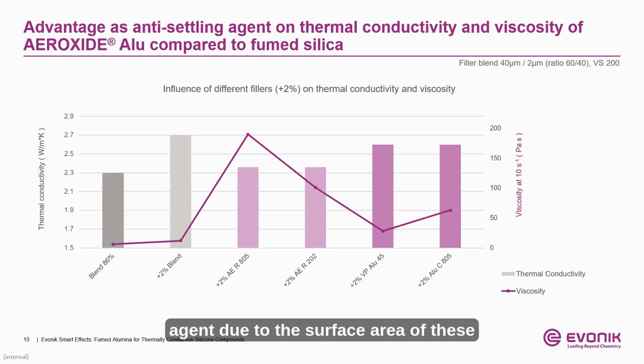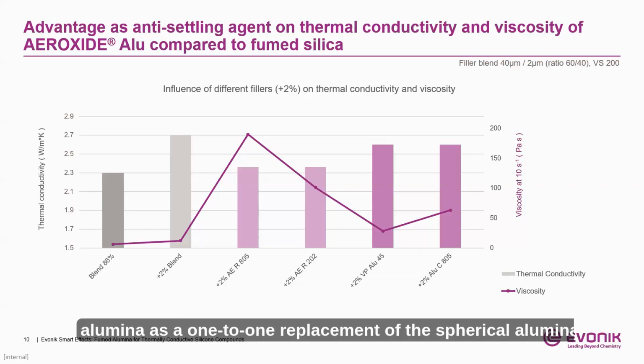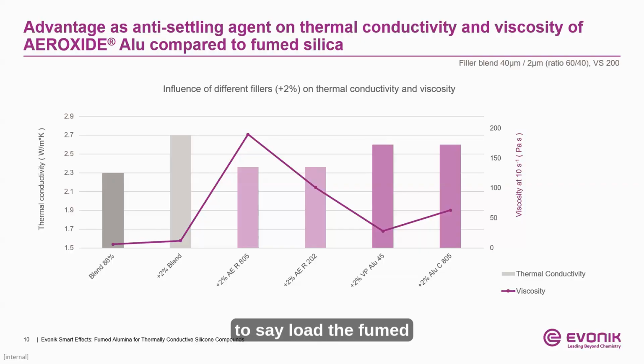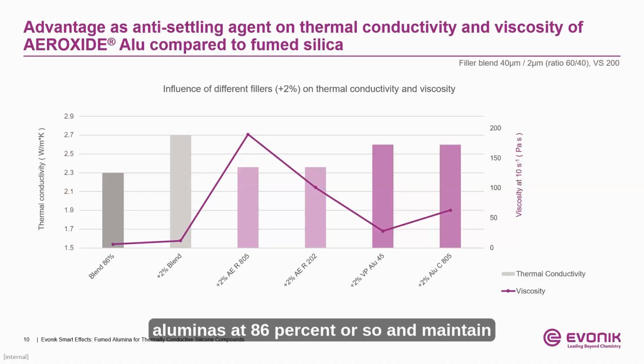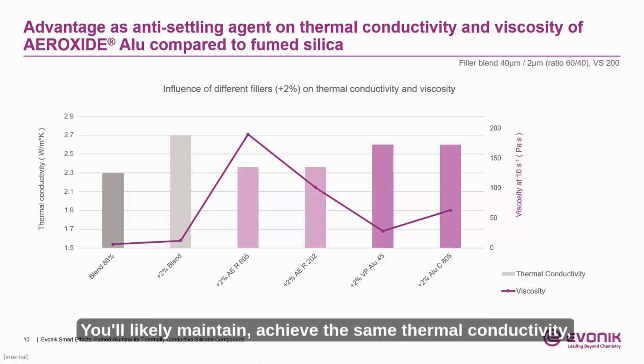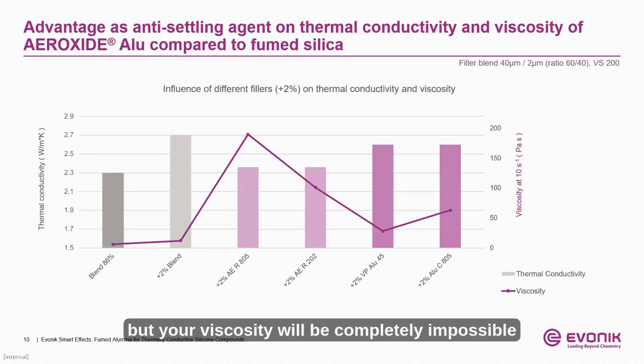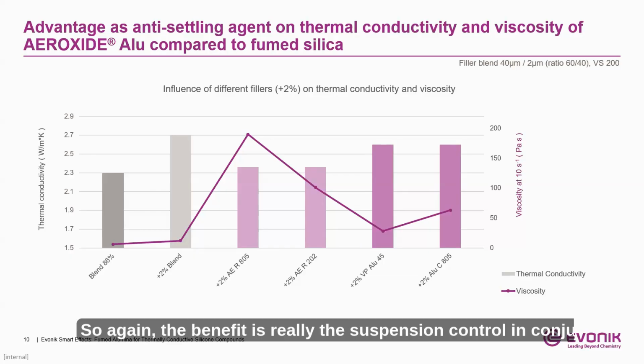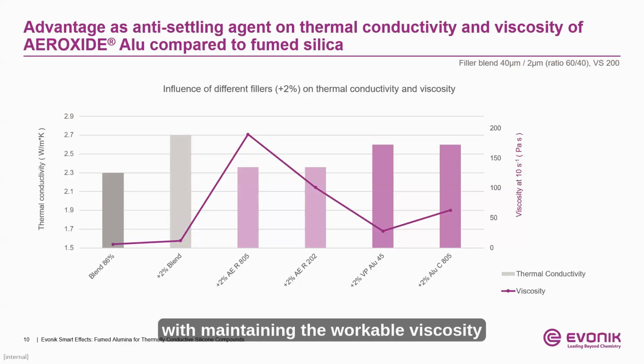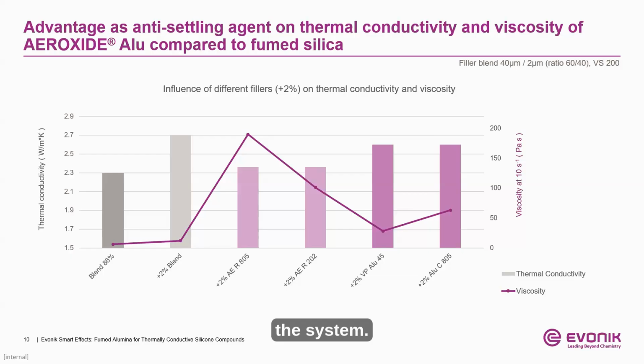Due to the surface area of these materials, their highly rheological nature, you'd never be able to really use the fumed alumina as a one-to-one replacement of the spherical alumina. You would never be able to say, load the fumed aluminas at 86% or so and achieve the same thermal conductivity. You'll likely achieve the same thermal conductivity, but your viscosity will be completely impossible to work with due to the rheological nature of these materials. So again, the benefit is really the suspension control in conjunction with maintaining the workable viscosity and the thermal conductivity of the system.